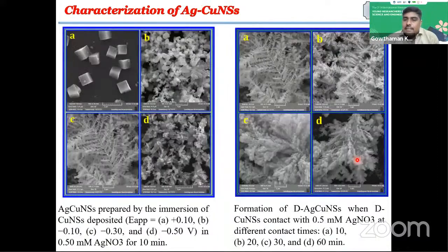And then the copper nanostructures deposited electrode is immersed in a solution containing only silver nitrate. There is no reducing agent, and there is no applied potential. So it's very interesting that the silver nanostructures covered the copper nanostructures. There is a formation of silver copper bimetallic nanostructures.